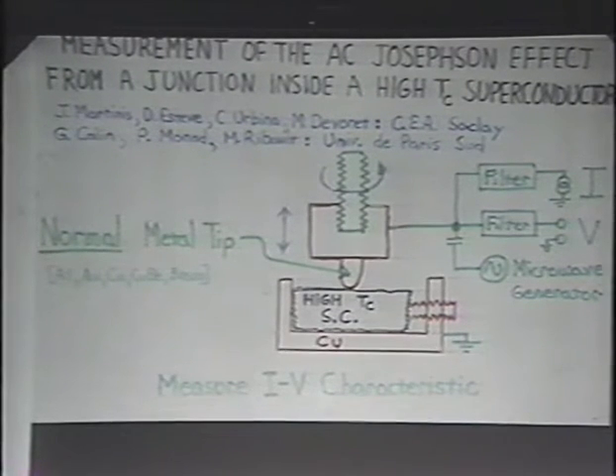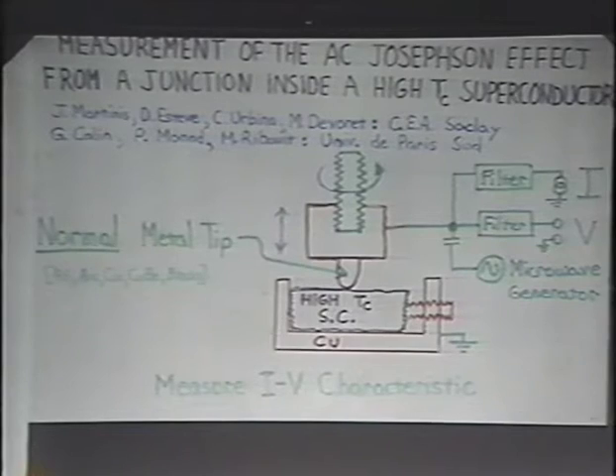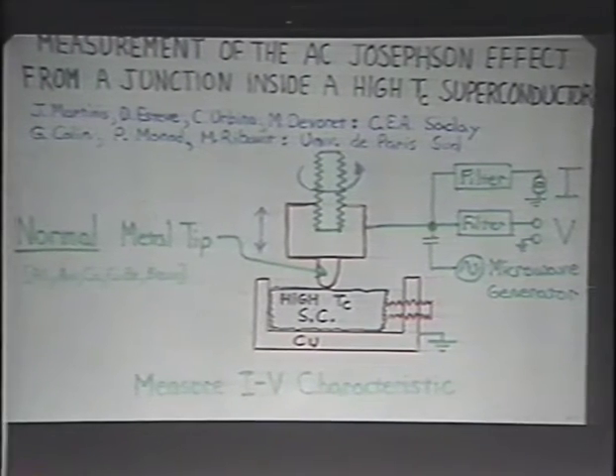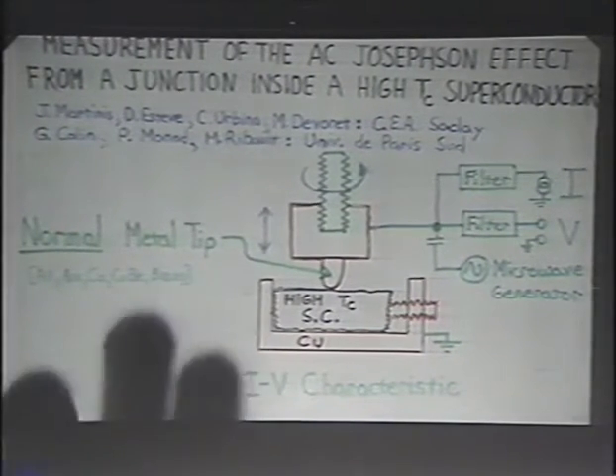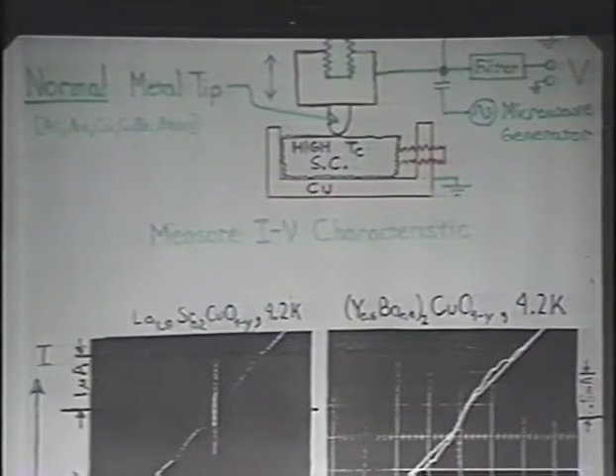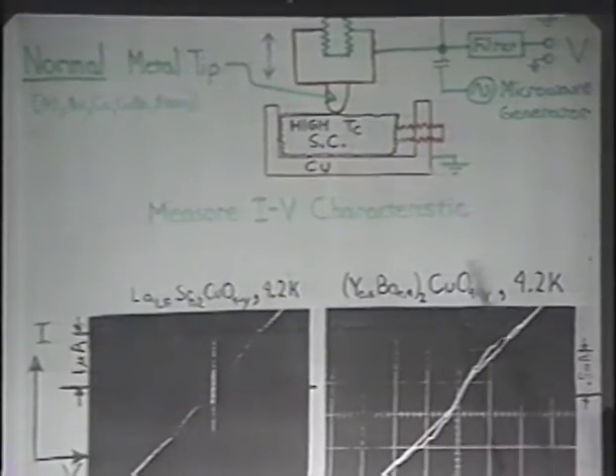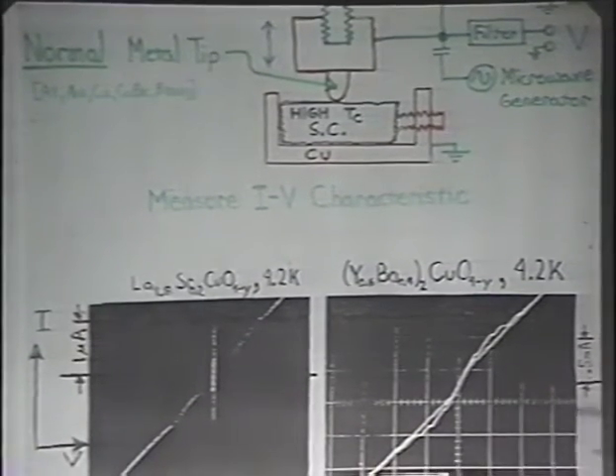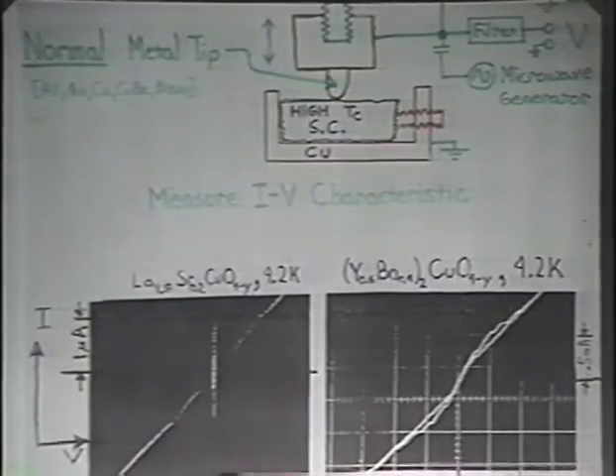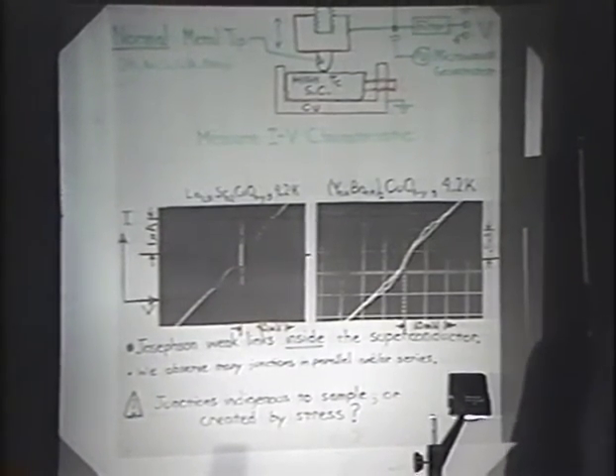And then we take a normal metal tip, and with the screw thread we push the metal tip onto our sample, and then we just simply measure the IV characteristics. What we find is something like this. For the strontium and yttrium compounds, these are sort of good characteristics we get maybe after playing with the system for 5 minutes, but by no means untypical. These structures, for example, this structure here, is very characteristic of a Josephson junction weak link.